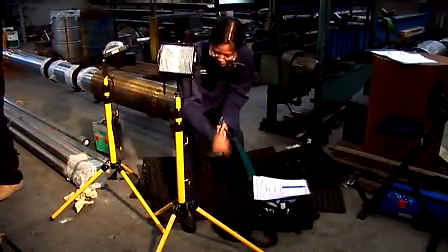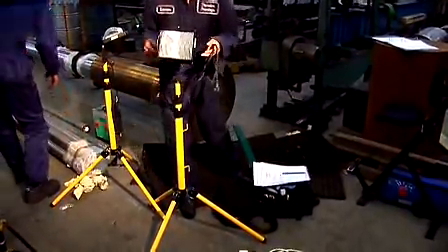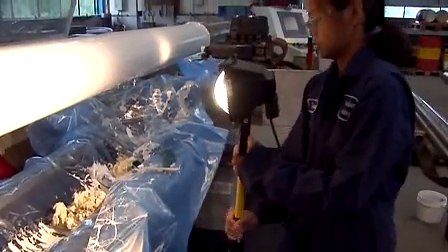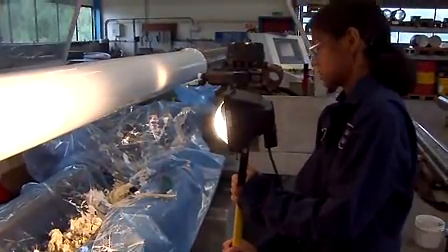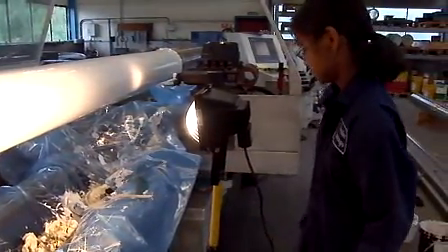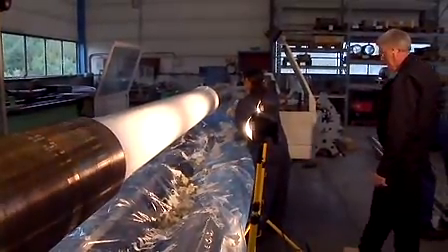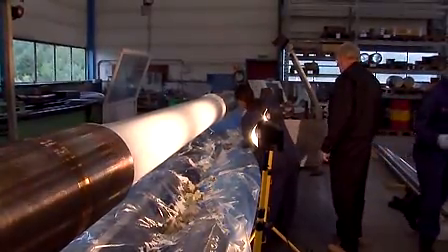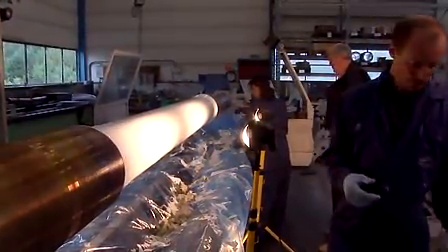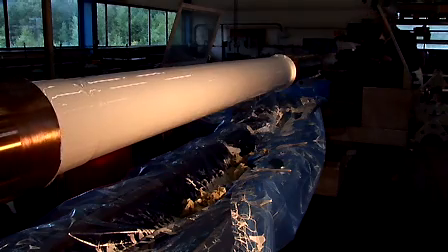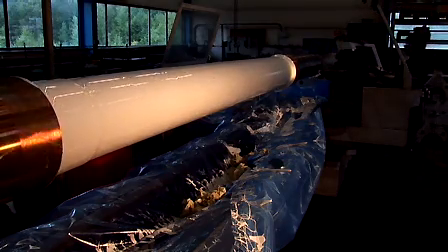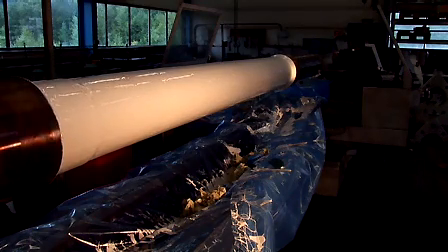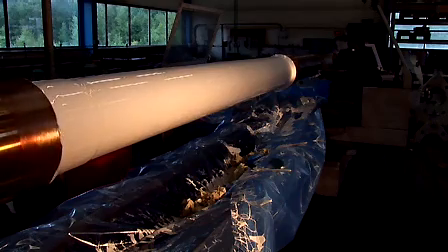Curing of the Thor Coat surface will be greatly accelerated with the application of heat. Ideal curing temperatures range between 20 and 40 degrees Celsius or 70 to 105 degrees Fahrenheit. At the lower range, allow a minimum of 5 days for full curing. At a temperature of 40 degrees Celsius or 105 degrees Fahrenheit, allow about 24 hours for curing. Using 500 to 750 watt heat lamps positioned 40 centimeters or 15 inches from the surface provides an ideal heat source to accelerate curing. Achieving the 2 millimeter or 80 thousandths of an inch thickness with a single coat is possible. If multiple coats are needed, apply each coat after the preceding coat has partially cured.